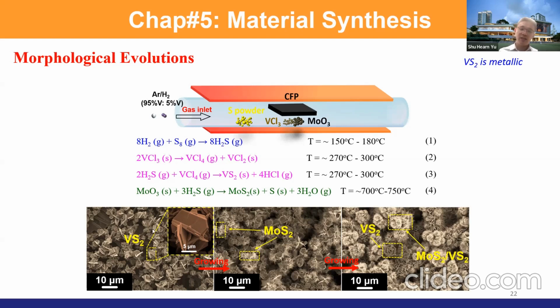The thing is that the vanadium disulfide is sensitive to moisture and is also conductive. So it's good to keep the VS2 underneath the MoS2. MoS2 is not so moisture sensitive, so it can protect the VS2. And MoS2 is not so conductive. VS2 is more electrically conductive. So with VS2 and MoS2 together, I want to see whether their performance can be improved. That's why I designed the experiment and tried to look for some interesting phenomenon.